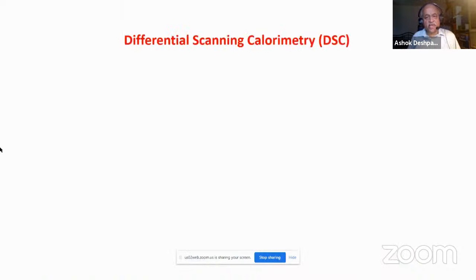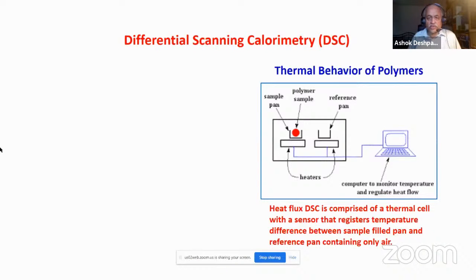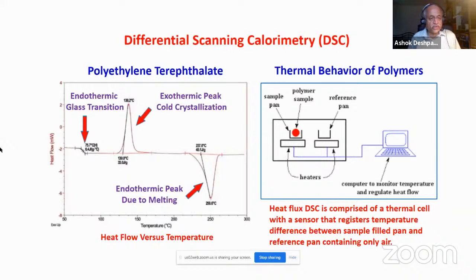Differential scanning calorimetry is based on thermal behavior of polymers. The instrument is based on a thermal cell which has a sensor that registers temperature between sample filled pan and the reference pan which contains only air. As we increase the temperature, the polymer undergoes various phase transitions, and depending upon if it is endothermic or exothermic, different amount of heat is needed to keep the two pans at the same temperature. So this is characteristic to a given polymer.